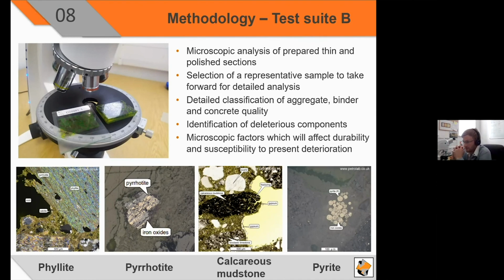On the left, we have the phyllite aggregate, which is primarily responsible for much of the free mica present within the Donegal blocks. This phyllite aggregate is very thinly layered and weakly metamorphosed, consisting of very fine micaceous muscovite mica. This is easily sheared and broken into the matrix, where it distributes in amongst the fine aggregate. Just over from that, we have pyrrhotite, in this example exhibiting oxidation to iron oxides in situ. The pyrrhotite is primarily present within the Dalradian metasediments, typically found in County Donegal, and is reasonably endemic to the phyllite lithology.